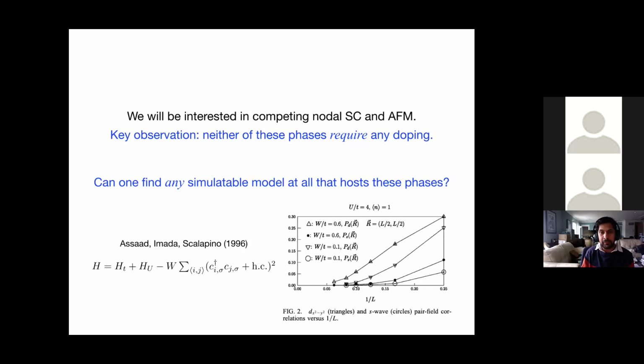And there's one very interesting proposal which came out when I was getting excited about calculus in my high school. This was a Hubbard model, the standard Hubbard model with an extra term, a kinetic energy squared. It has signatures of d-wave superconductivity, but the signal is very small, as you can see here. This is the d-wave order parameter, and it's about 0.01, and this is 1 over L. So you have to argue that as L goes to infinity, it remains non-zero. It's not easy to argue that based on just this data. It looks perhaps promising. It's at least more prominent than s-wave, but to really conclude that it's non-zero in the thermodynamic limit is not going to be easy unless one does more numerics, and one should do it.